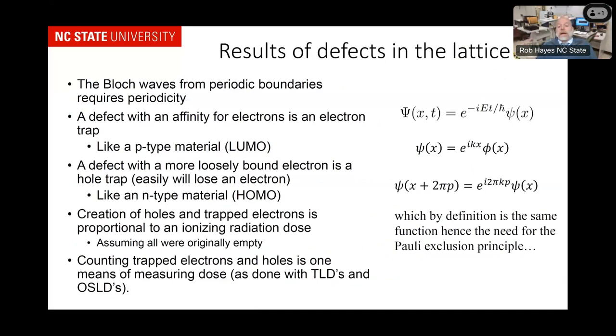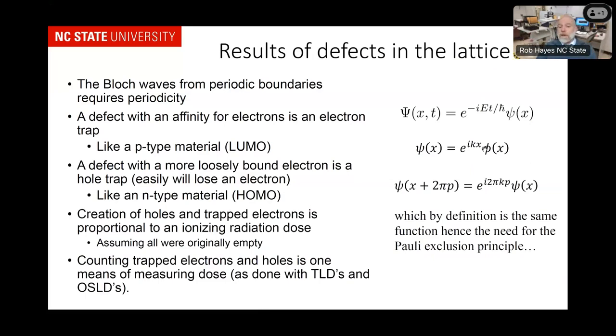Because of that, the Pauli exclusion principle says you can't have the same quantum numbers, so they have to slightly perturb themselves and become different energies — effectively a band, a uniform distribution. Whenever I have a deviation from periodicity — any kind of a defect, an interstitial, a vacancy, an impurity — that gives rise to the potential to have a stable energy state or quasi-stable energy state between the valence and the conduction band.